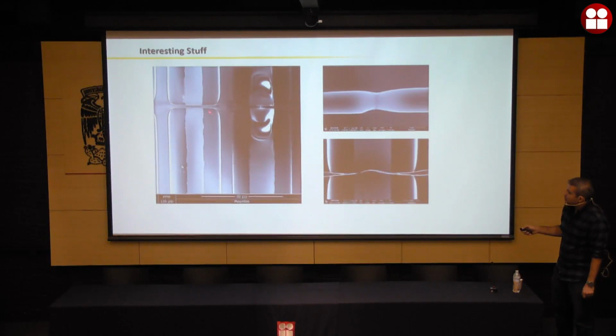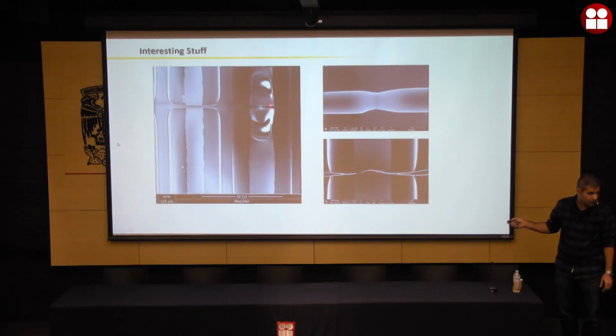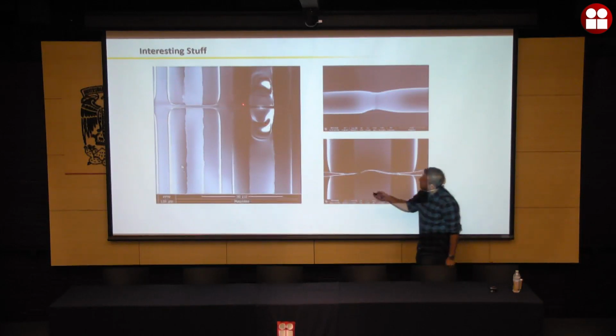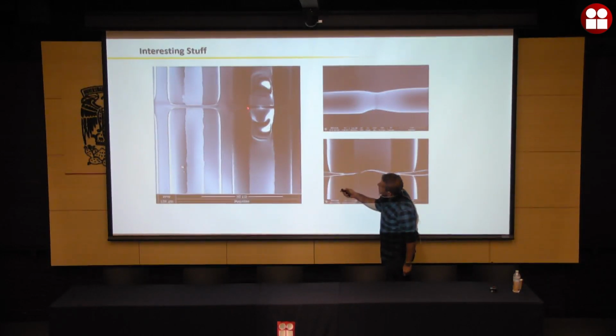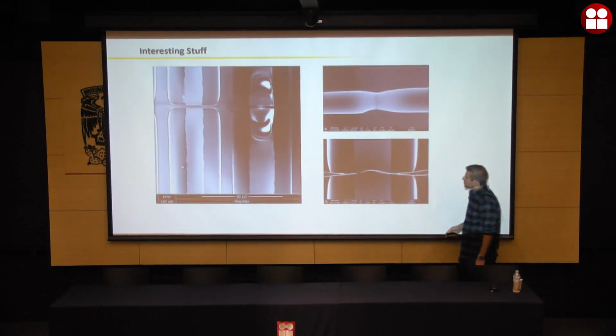So this is the fabrication process. Let's assume that you have this microfiber here sitting on your electrode, and you apply the potential here, it heats up, and it melts down and creates this gap. Do you see this effect in the back? This is because of the high temperature at this gap. It is so high that it is melting the SiO2 on the surface of your silicon wafer. So this is a very interesting phenomenon. And if you're paying attention here on these corners, you can see sublimation residues of SiO2.